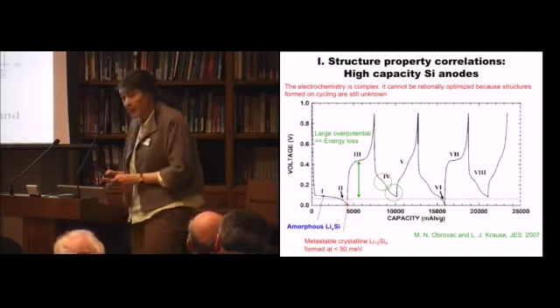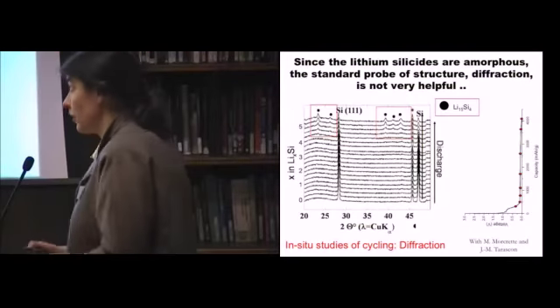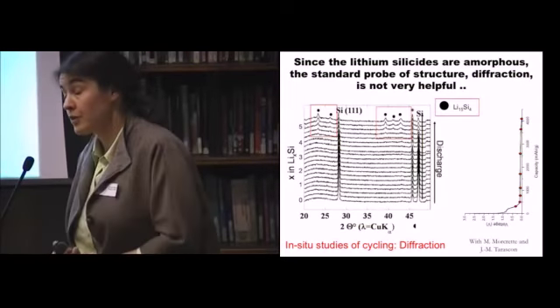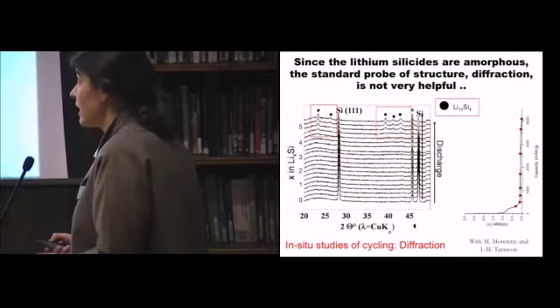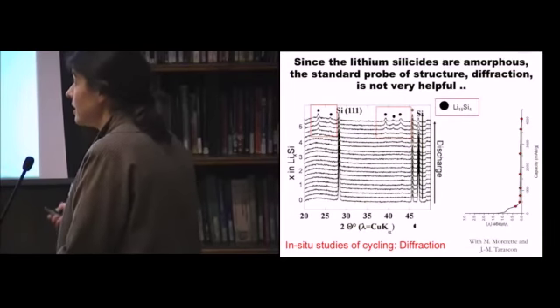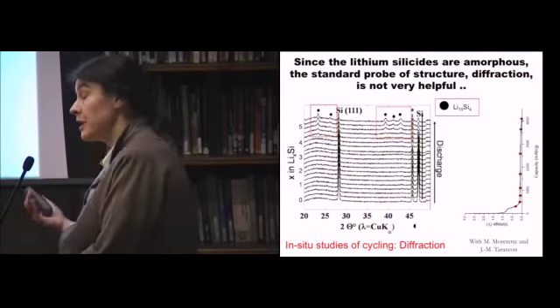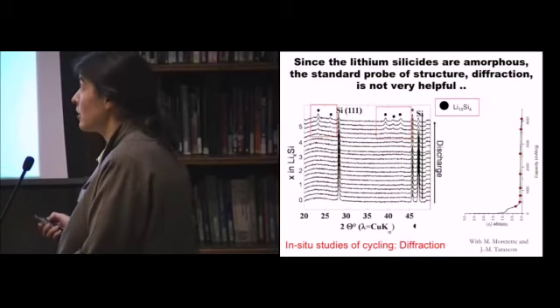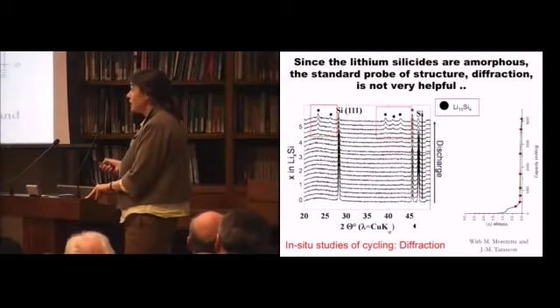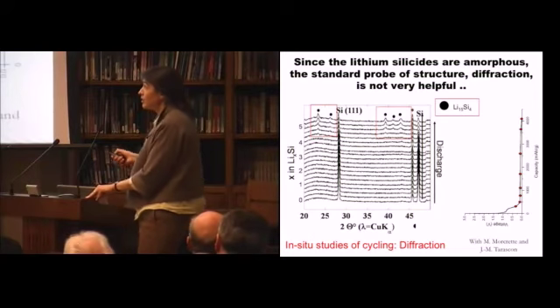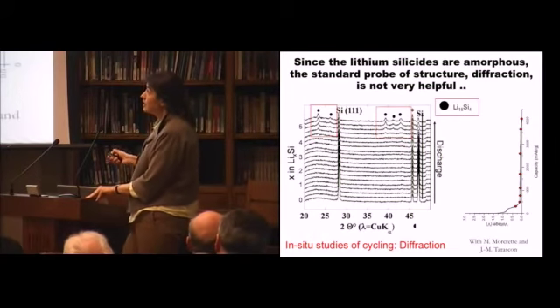So normally, what people would do to look at these types of systems is X-ray diffraction. You take a diffraction pattern and you see a series of peaks, and from those peaks you can say something about the structure of the material. But because your crystalline silicon converts to an amorphous phase, you don't see anything until you get to the bottom of discharge, and you see these peaks corresponding to a metastable phase.